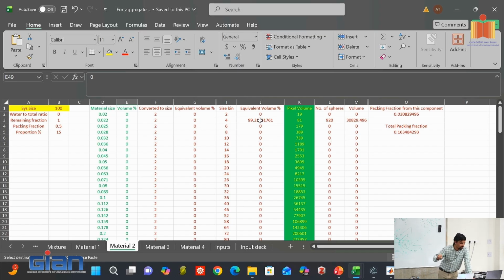For this, the initial value itself did not work for 50. I had to go to 35% as the packing fraction by the point I actually got it. Speed may not be optimized, but for random seeding, when you go to larger particles, you see the volume fraction is decreasing. You can't randomly distribute a single smaller particle size to get lesser porosity. At a point you will have to have different sizes so that they can fit in. Because I did not have many different sizes, I just selected 2, 4, 8, 16.